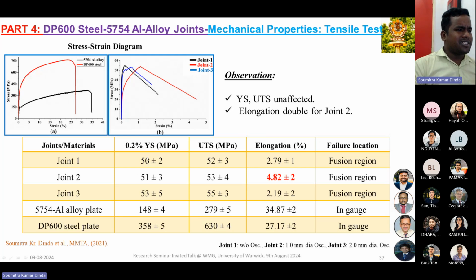Now let's see the yield stress. The base metal yield stress is 148, 358, but the yield stress here is quite low, near about 50 MPa. But UTS is very close. If you use the oscillating beam for joint 2, with 1 mm oscillation diameter, we found the elongation is double compared to the without-oscillation condition, that is 2.79 to 4.82. But in joint 2 and joint 3, it is again decreasing. And check the failure location: all joints failed at the fusion region, not like the previous condition where the joints failed outside the gauge length area.